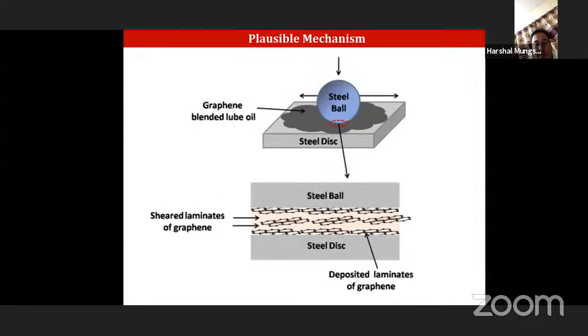And about the mechanism, why the friction or wear is reducing, you can see in this slide. I have shown this graphene blended lube oil. What is happening? Because this graphene sheet is present in between the steel ball and steel disc, or we can say in between the interacting surfaces, that graphene material will prevent the direct contact between the two interacting surfaces, and that's why friction is reduced. That's why wear is reduced. Wear is reduced means preventing the loss of material because of this relative motion, and this is the mechanism of how we can prevent the direct contact and reduce the friction and wear. So this is one example.